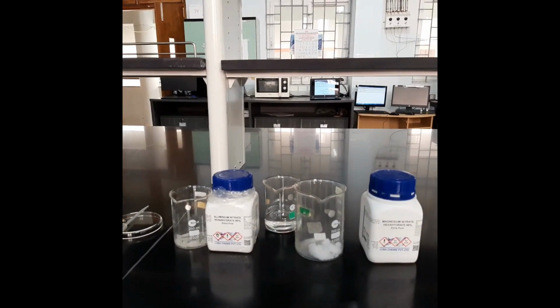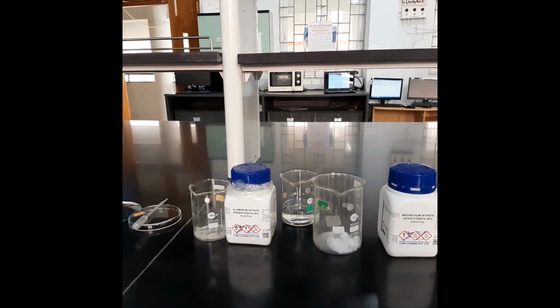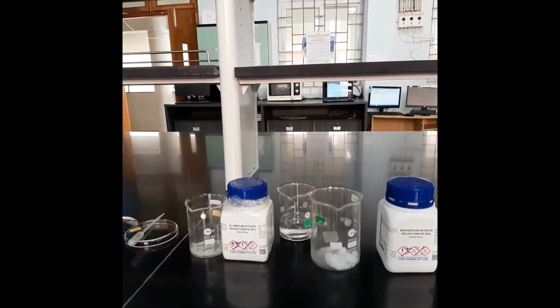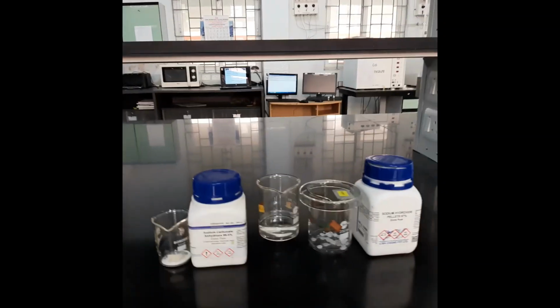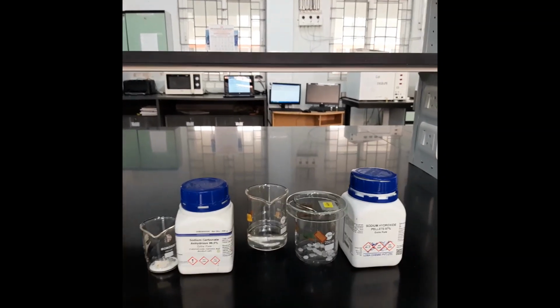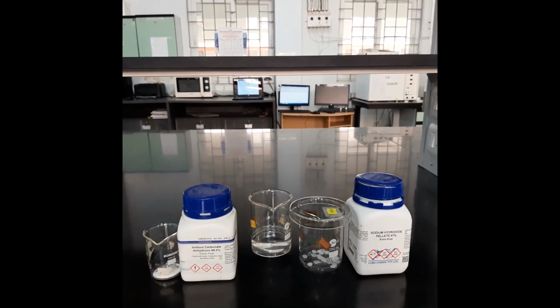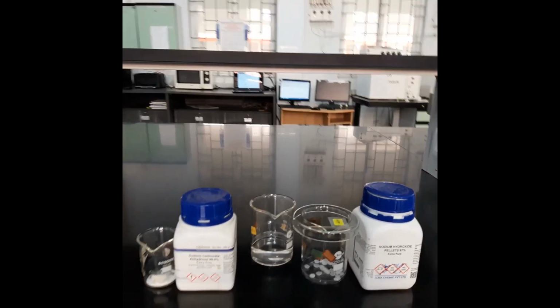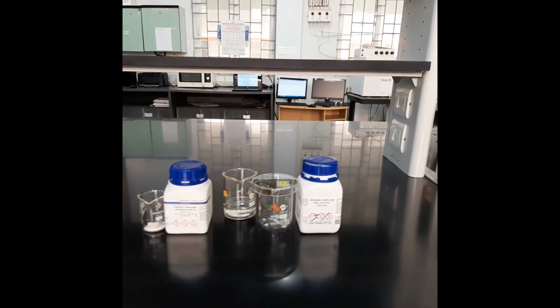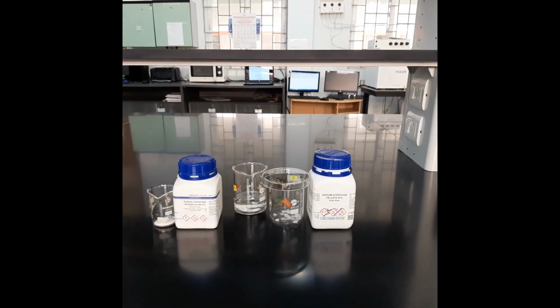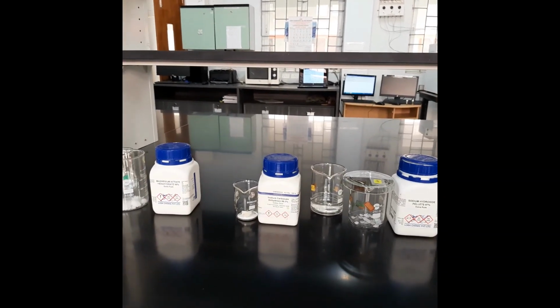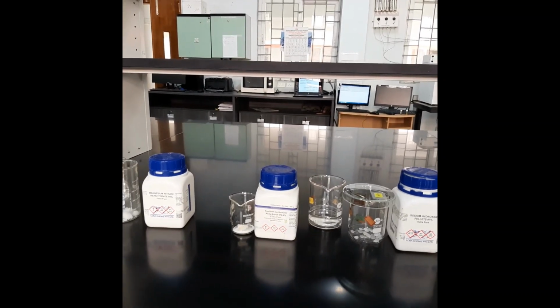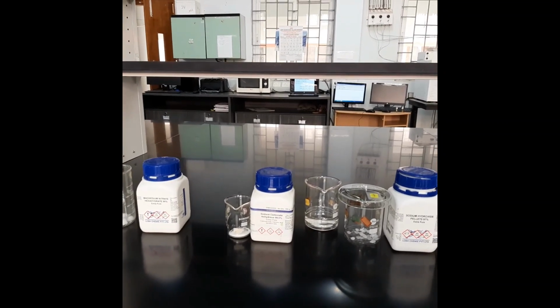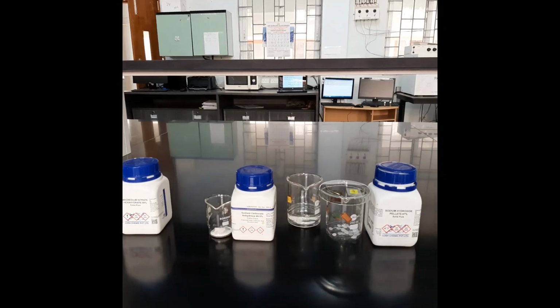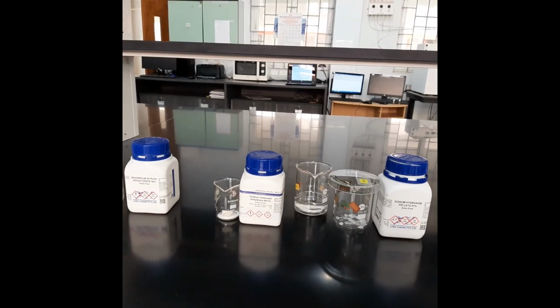Nitrate is always the best source because it is easily soluble and it can be easily decomposed. And then we have the base. Base is required for the hydrolysis, because it is a solution synthesis. In this synthesis we will be using sodium hydroxide as a base and sodium carbonate, and the carbonate is going to play an important role in the intercalating space. So the more carbonate there is, the more aluminum will be incorporated into the magnesium sites.